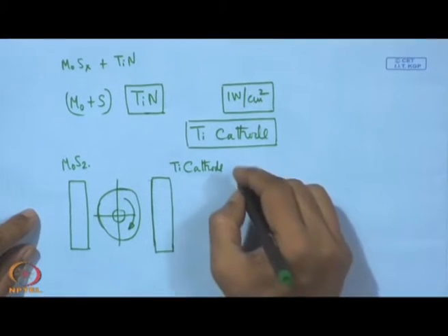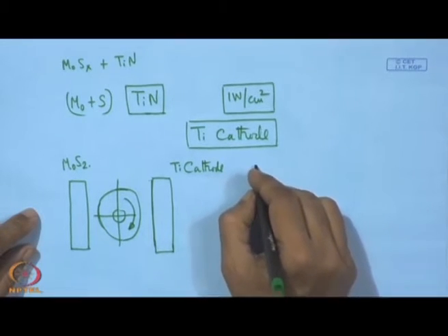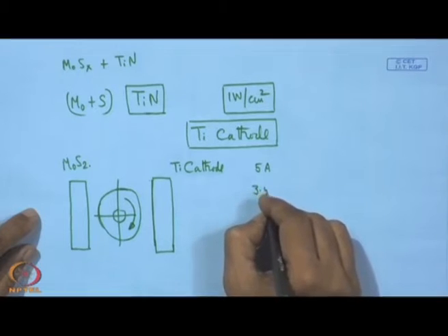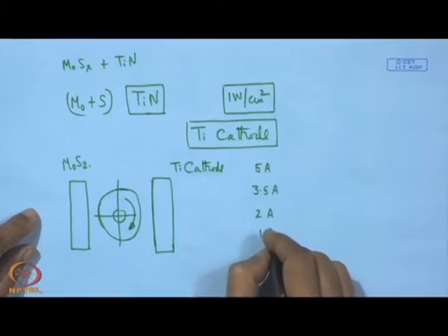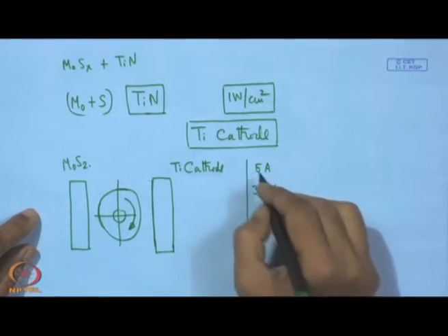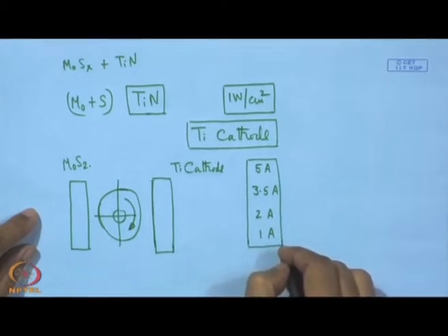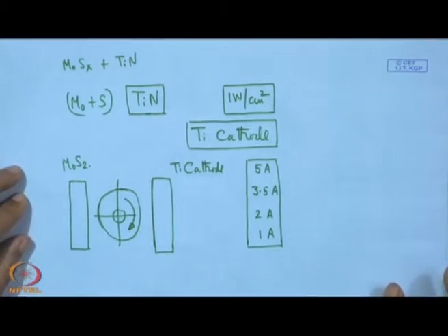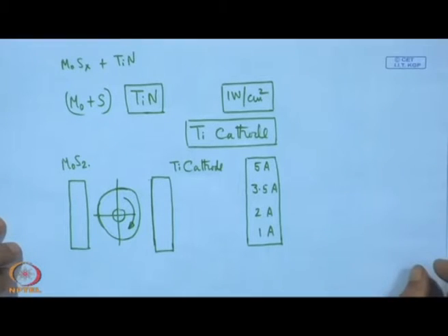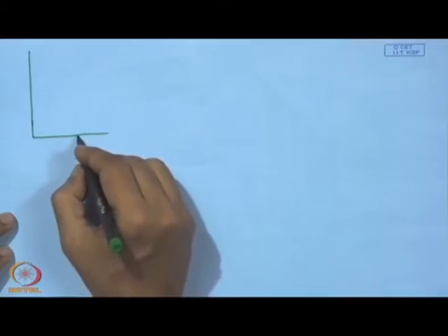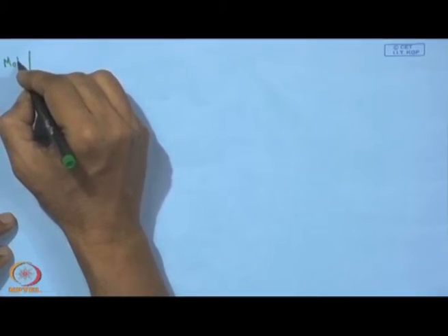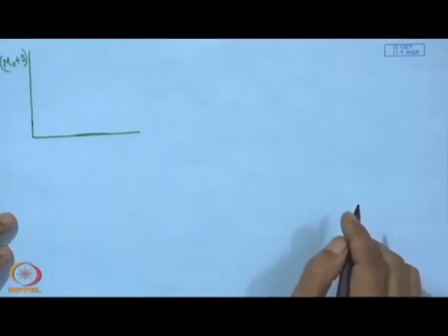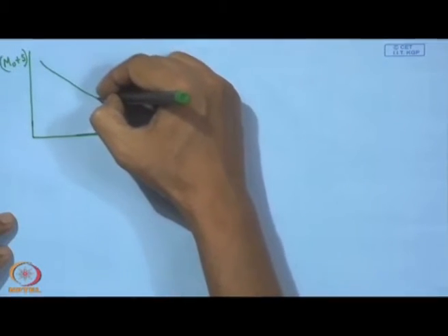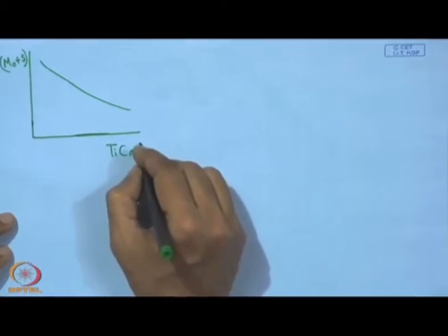The titanium cathode current could have been varied, say from 5 ampere to 3.5 ampere. This is just by way of illustration. Any other combination is also possible, and with that we can also see the effect of this on the overall performance. Now, with this we can find the percentage of MoS2, so what we get is something like this. So, it is the titanium cathode current.